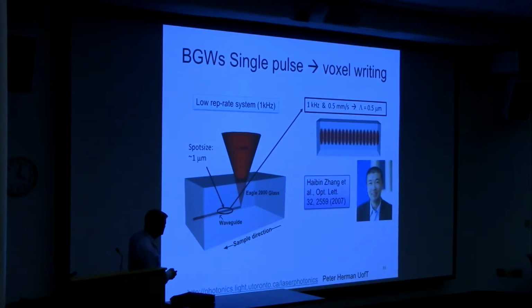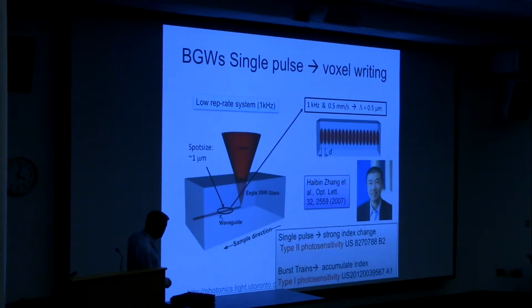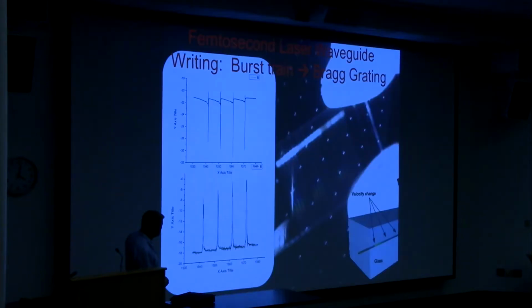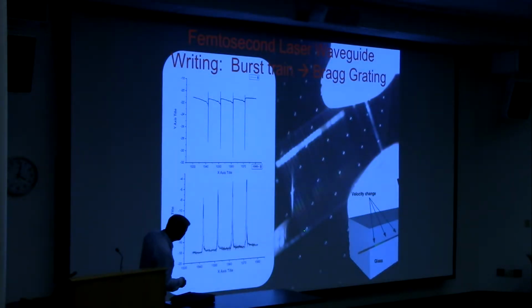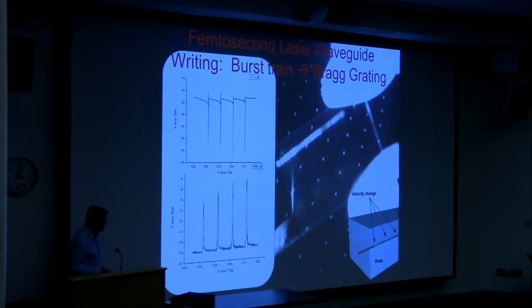And so we're able to build these waveguides simultaneously with this, have made several publications over 10 years ago now and a couple patents. And here's how they look. So along here you see parallel laser-formed waveguides, the white zones, and you can see the scattering of light at optical wavelengths. You can see the blue to green, showing that there's a structure there on the scale of wavelengths. And so when you pass light through this, you'll get a notch filter in transmission or in reflection. And what we did is we just, with computers, shifted the writing speed and shifted the Bragg resonances. So we have narrow band filters formed this way arbitrarily. So this is a really important tool.